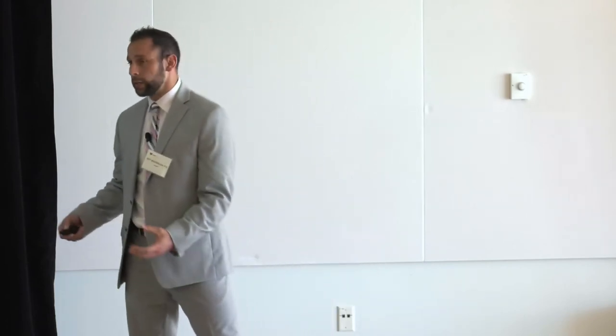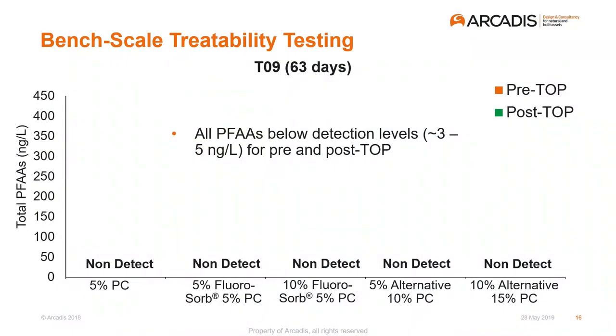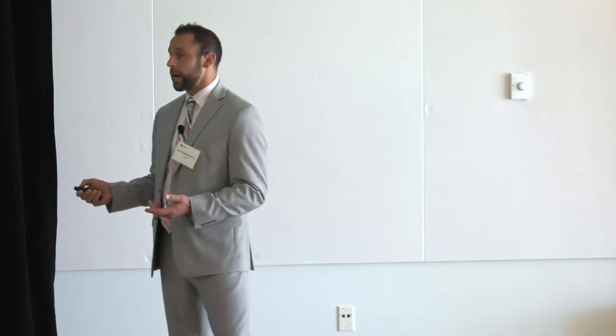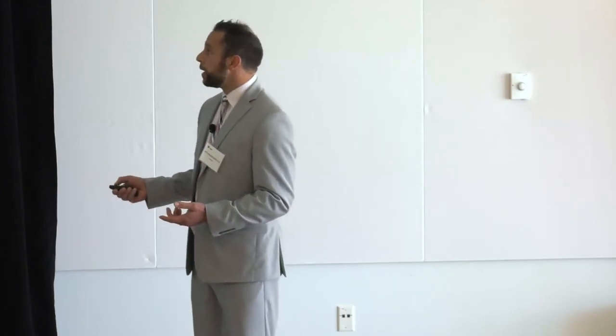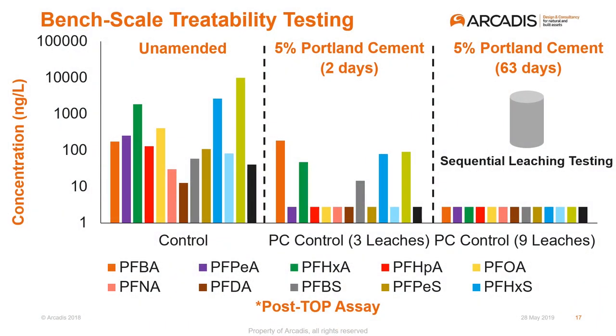We created a concrete cylinder that had a permeability of about 10 to the minus 4 centimeters per second, leached it 9 times over 63 days, and surprise, surprise, the concentrations went down. So every time we took the cylinder out and put it into a new bath, we had to permeate the same surface area to get at the access. So had we sat this core for 3 years and leached it again, I bet PFAS comes off of it. But it's a time-invoked bias. So we need to be very cognizant of that when we picked our time series stamp at 3 days to understand that by 9, everything's going to be non-detect, okay? So we picked 3 as a representative, and there's something else that we're going to add to try and close the mass balance that I'll talk about at the end of the presentation.